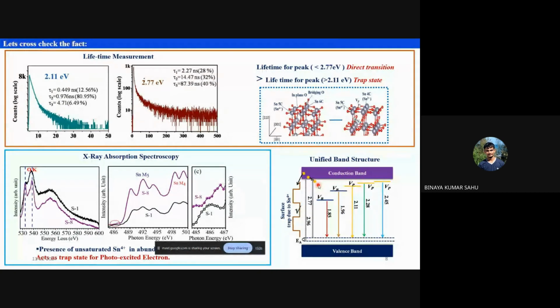But there are two peaks, this 2.77 and 2.96. Generally, their intensity is very much less in the whole spectra because there is a defect, a surface defect lying at the surface. Because of this Sn4+ site, because of oxygen, the electron will come here and will be trapped here. So we cannot see the 2.77 and 2.96 clearly. That intensity is very much less. So if you understand this much, that is fine.